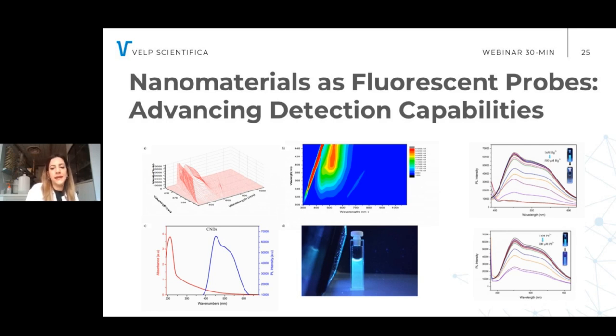First of all, the fluorescence: it's possible to see from this picture how fluorescent these carbon dots really are, how high the fluorescence emission intensity is. By adding heavy metal ions into the solution, it was possible to see a quenching of this emission, especially with mercury, at high concentration of which the emission was completely switched off.